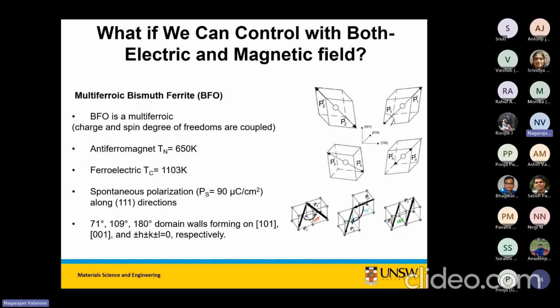Why bismuth ferrite? Bismuth ferrite is a ferroelectric, but of course it's also multiferroic from the iron. The spin comes from the iron. So if we control both the electric and magnetic field, the holy grail is that we can manipulate the magnetic moment by switching the ferroelectric polarization. I think in the beginning, a lot of people tried to do that, and then we now know that the coupling is not direct, it's cross-correlated, and the coupling is not as straightforward as people originally envisioned.